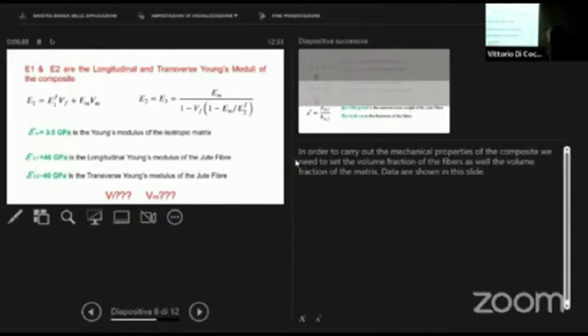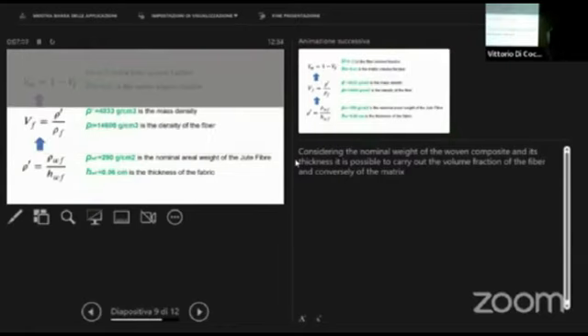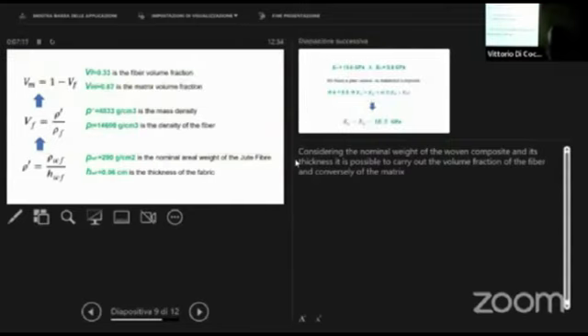In case of the isotropic matrix, from the technical database, we have 3.5 gigapascal, and about the fabric, we have 40 gigapascal. So we have determined the volume fraction of the matrix and the fiber, given the nominal area weight of the fiber and the thickness of the fabric. Simply, it is possible to determine the amount of fiber inside of my plate, and as a consequence we have determined also the amount of the matrix.